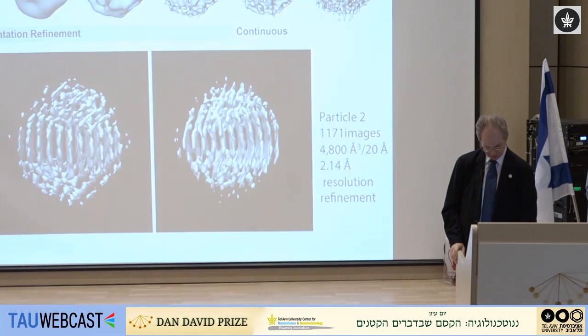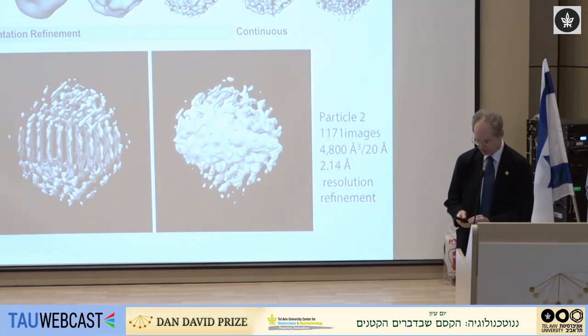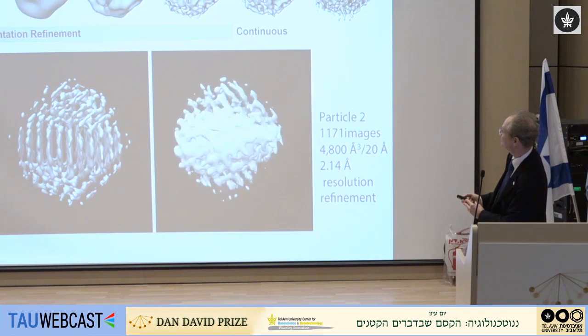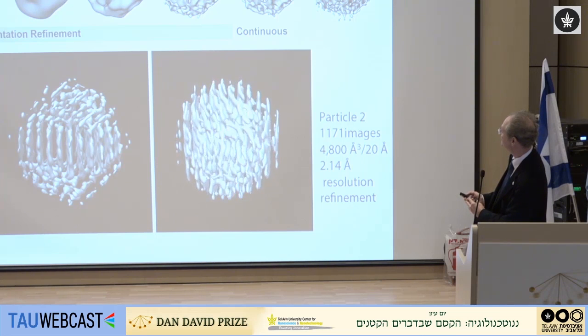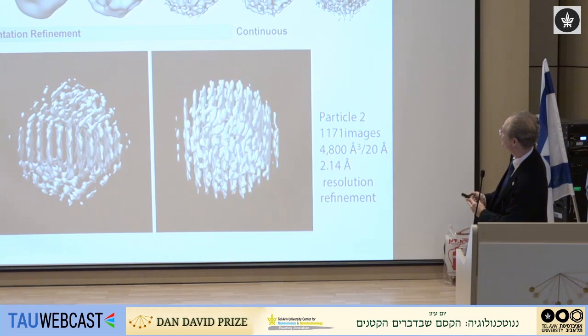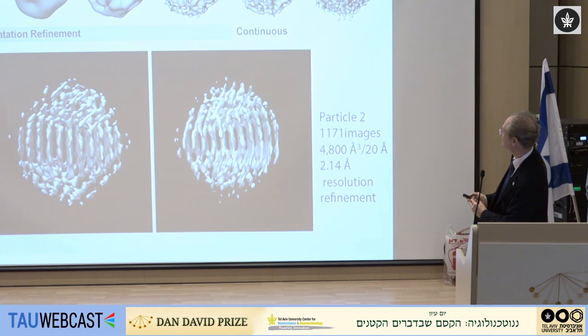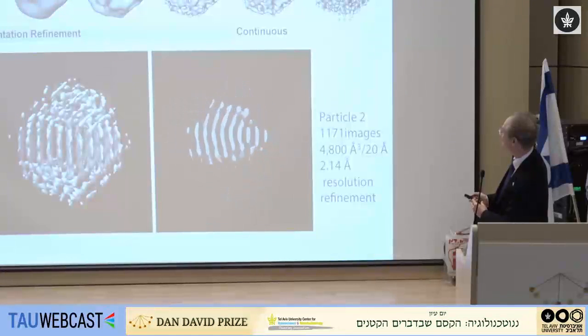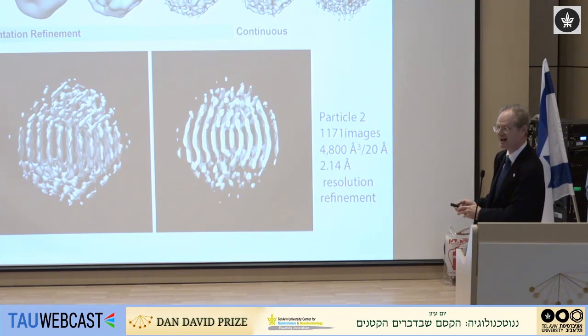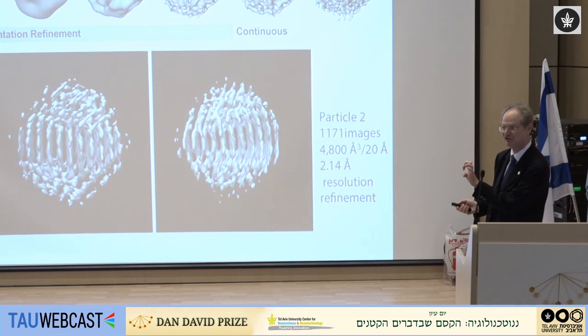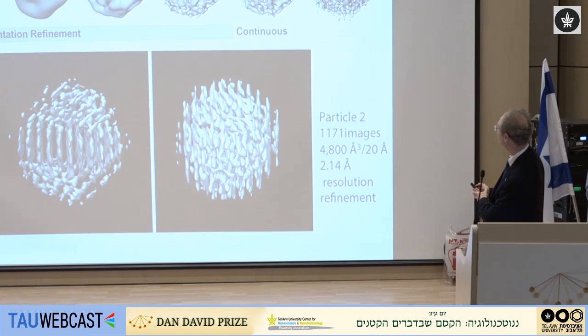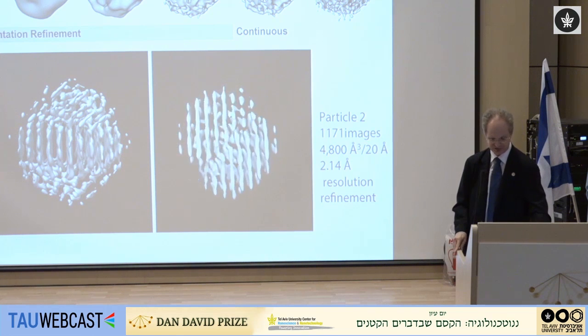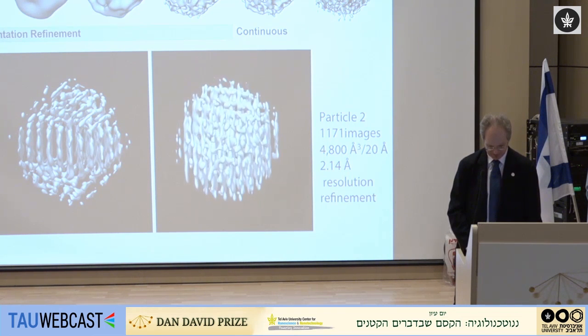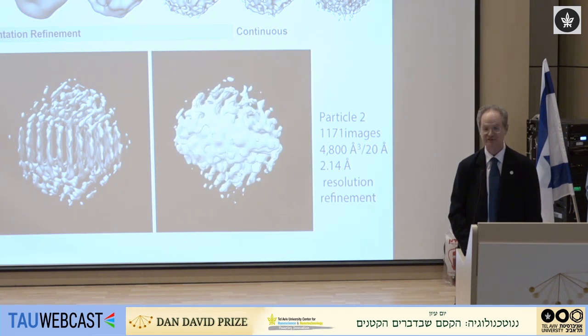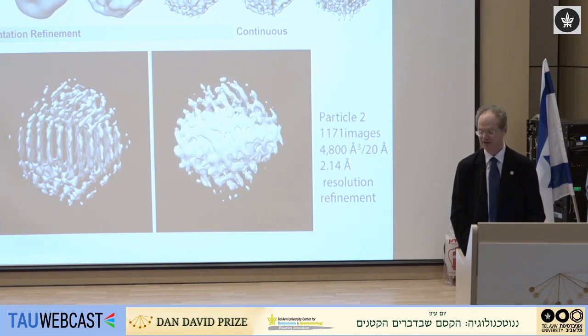And so that's done by a kind of simulation, in which we start with a uniform density and we see what kind of diffraction pattern that would create. And then we allow a Monte Carlo-like fluctuation in the electron density, and we see if that gets closer or not to the observed distribution of diffraction patterns. And then we repeat that over and over and over again with both a discrete and a continuous region to that process. And if we do that enough times, eventually we're able to back out the best fit that we can get for the amount of data we have and the amount of noise that's there.